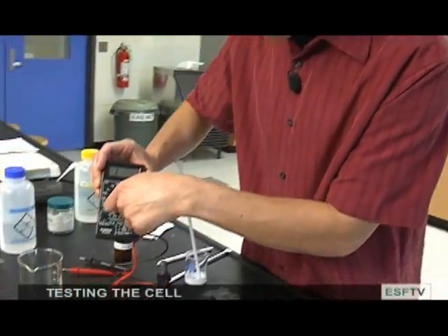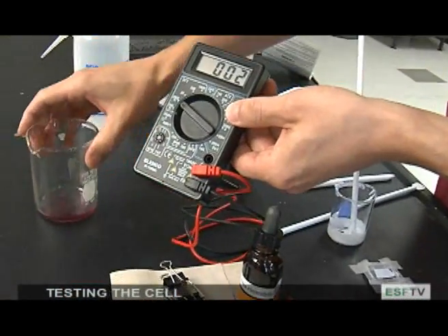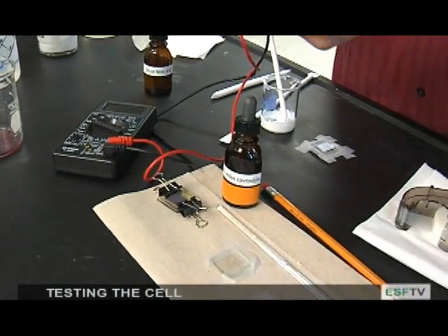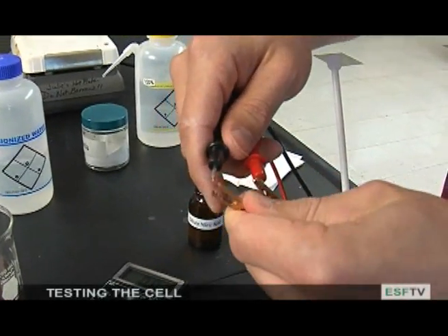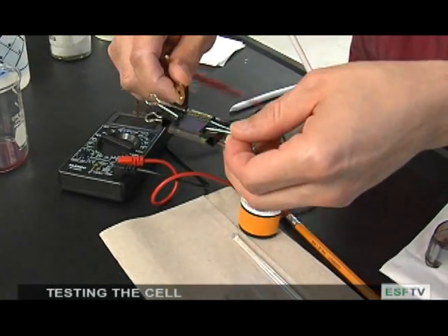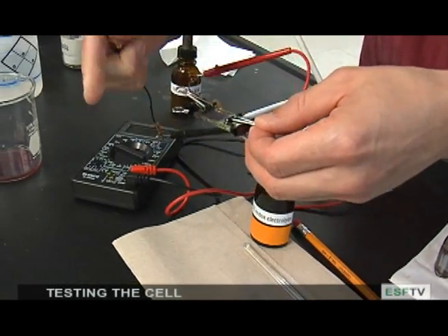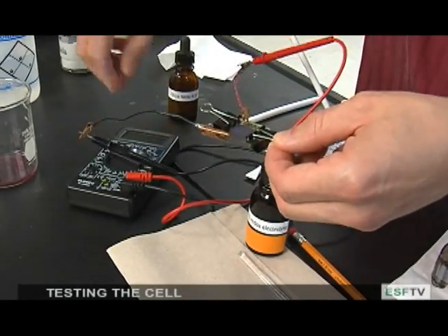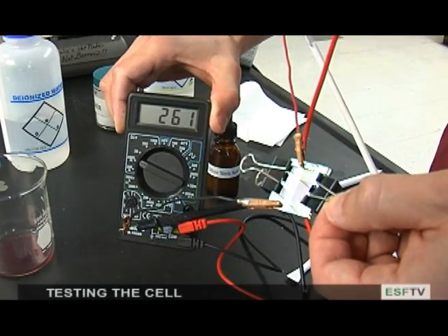So let's take a look. Taking our multimeter again, we're going to change it to millivolts. Depending on what type of multimeter you have, the way you change it will be different. To make the measurement a little easier, I'm going to apply some alligator clips to the probes and then those alligator clips are going to get connected to the cell. As I connect it to the cell, we should start to see a voltage. In fact, as I move it into the light, we see over 250 millivolts right now. And that's just using room light. So as you can see, we were able to make a dye-sensitized solar cell, a cell that produces electricity just using simple blackberry juice.